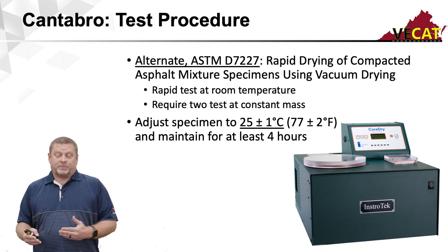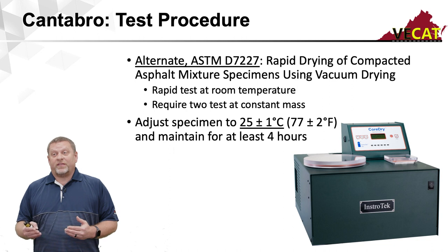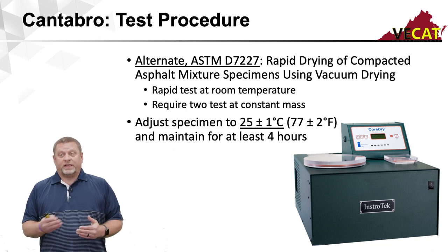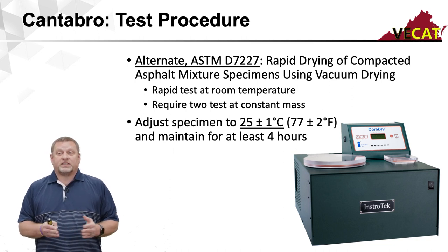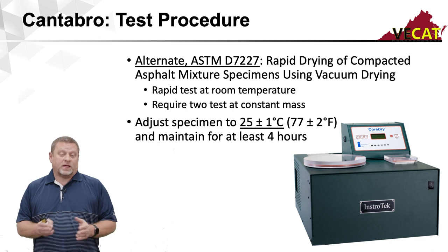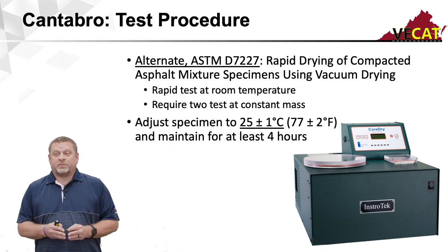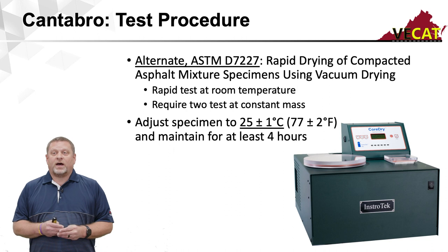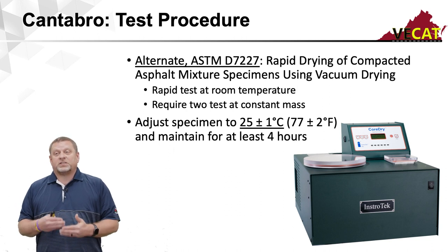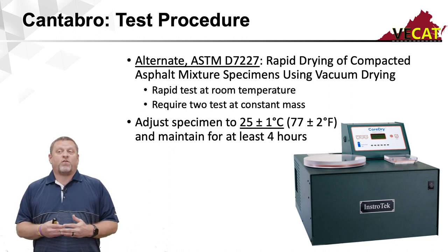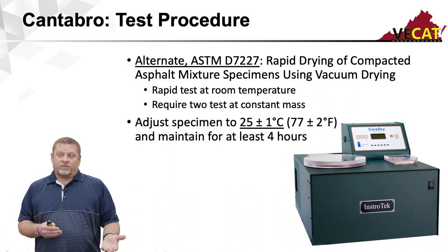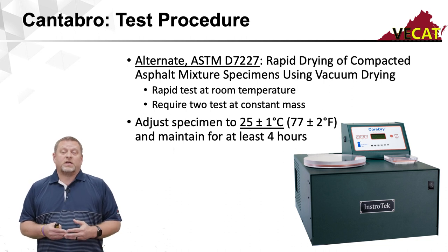The way I verify that I've dried them is I check my weight after each cycle, and I need two tests in a row at constant weight or constant mass so that I know my specimens are completely dry. I then need to adjust these specimens to testing temperature for 4 hours. Again, 25 plus or minus 1 degree Celsius, whether it be an environmental chamber or something, but they do have to stay dry.